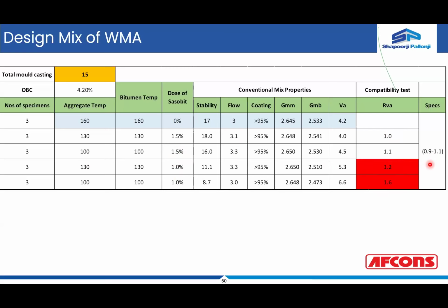So the method of mix design remains the same, the test remains the same, but the mixing and compaction temperatures need to be changed and corrected, and you need to see the parameters which will be in the form of 0.9 to 1.1. So this air void ratio is basically giving you an indication of what should be your optimum dose. Now, if you do further trials by reducing the dose by 0.1%, like 1.4, 1.3, 1.2, 1.1, you will get an idea. In case of 1.4, if my temperature is 130 and 130 and I reduce my Sasobit dose from 1.5 to 1.4, what will be my air void ratio? It will be close to 1.01, 1.02, 1.03, 1.04, 1.05, or 0.9, or 1. So that is giving you an envelope: what will be my optimum dose of the additive which can be used to convert a given hot mix into a warm mix.